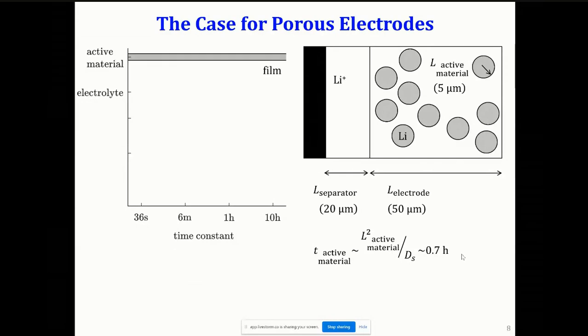The penalty that we pay is that now the lithium ions, which were just moving across a 20 micron length, would have to travel a much larger distance if they want to meet the particles towards the other end of the electrode. So it's just that the geometrical length changes. On top of it, now it's not a clear medium. It has to go through the crevices between the particles, which would introduce additional constriction factors, which we represent by epsilon, the porosity, which is nothing but the volume fraction of the electrolyte phase, and tortuosity, which is the longer path it has to take to reach the internal particles. And it now increases the time constant for electrolyte diffusion.